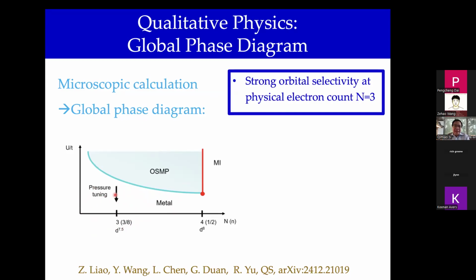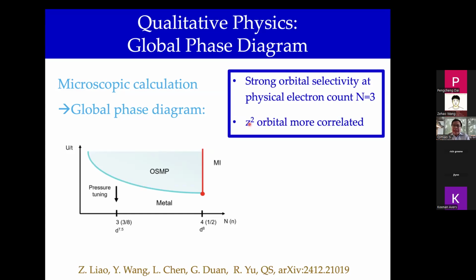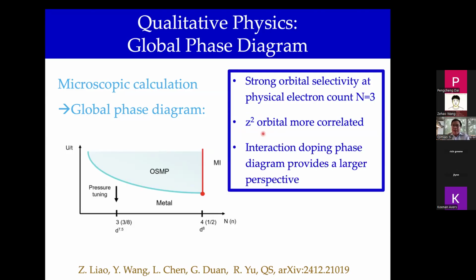So for example, if I want to think about the physics here, I could use this anchoring regime and perturb away from it, and that provides a way of thinking about interaction effects. In further detail, I now stress the 3dz square orbitals are more correlated, experience a strong renormalization effect, and that will become important when we think about spectroscopy in the normal state, but also in connection with the kind of superconducting pairing state that can develop. And also, I already mentioned that by looking at the problem over this wider perspective of the electron filling and interactions, we can find some anchoring regimes to think about the physics in the physically relevant regime.